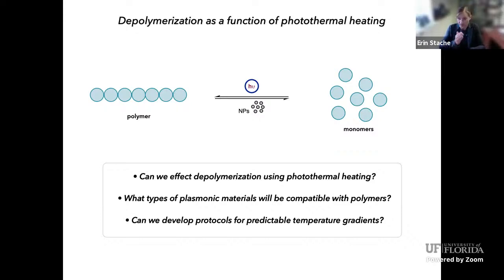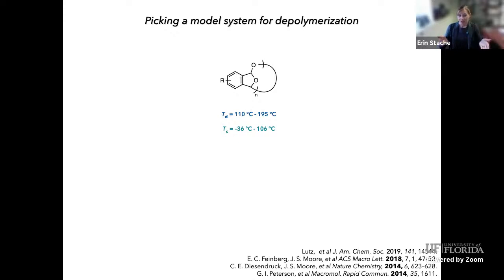Can we say, okay, we want to get to this degradation temperature. Can we get the right material? Can we get the right wavelength? And can we get the right intensity? And then can we tune that so we might be able to do selective depolymerization of polymers based on their degradation or ceiling temperatures? So this is what we set out to do, which is a very, very ambitious idea. And to start, we wanted to pick a model system for depolymerization, something that was well behaved with depolymerization, so we could really study the photothermal heating effects using our particles and our lighting setup.